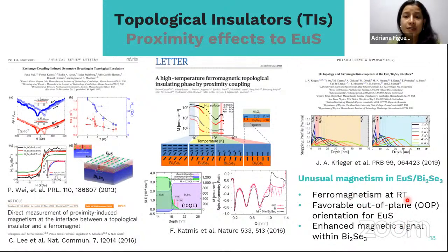For example, they have observed ferromagnetism at room temperature, even though europium sulfide is magnetic only up to 15 Kelvin, in principle, but they report ferromagnetism at room temperature. Also, regarding the anisotropy of the stack, they say that an out-of-plane anisotropy orientation is favorable in this stack, instead of the in-plane orientation that is usual for bare europium sulfide.